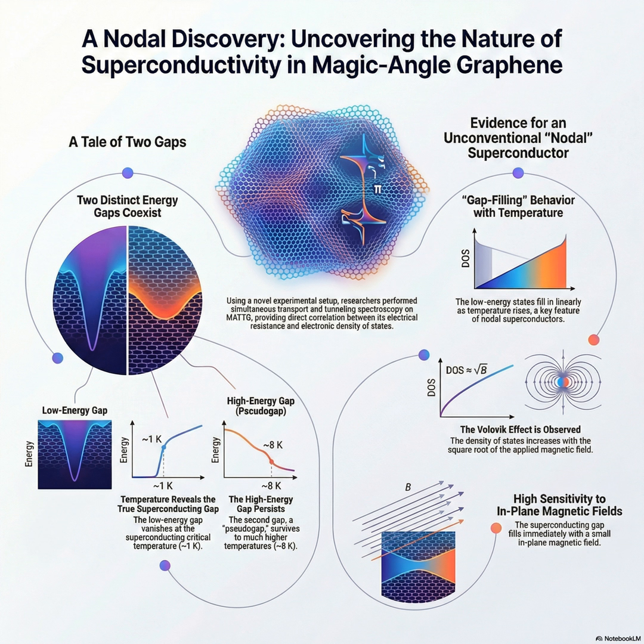They track something called the zero bias conductance. To keep it simple, that's just a measure of how easily electrons can move when you apply almost no pushing force. And they looked at how that measure increased as they warmed the material up towards its breaking point, towards Tc. Exactly. Now, in a conventional system, that perfect bubble shield, you wouldn't see many excitations until you get really close to Tc and the whole shield just collapses.